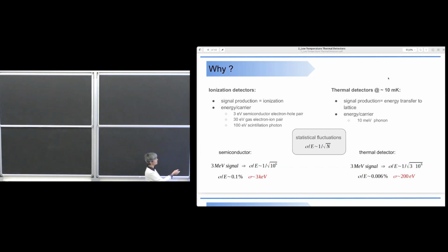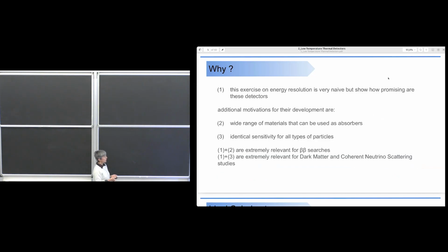Germanium can be used either as an ionization detector because it is a semiconductor, but it works also as a thermal detector. So you can compare exactly the same kind of solid. You will have exactly the same energy deposition when a particle crosses the volume. Of course, you need to have exactly the same volume. And the main difference is that the mechanism that produces the signal carrier is completely different. So this exercise on the energy resolution is really naive, but can show you how promising this technique is.